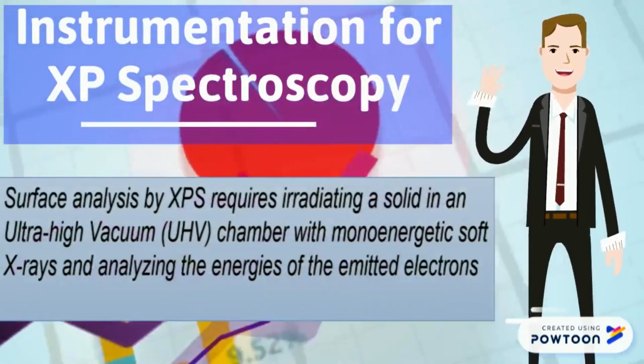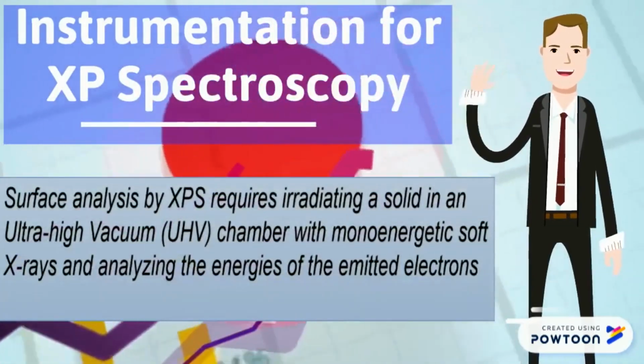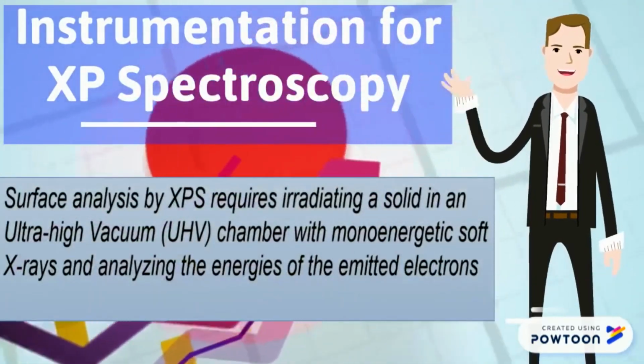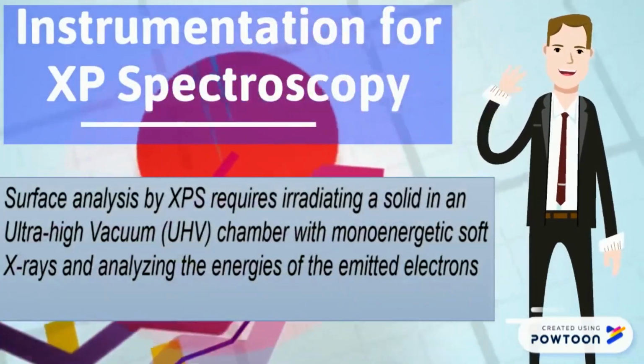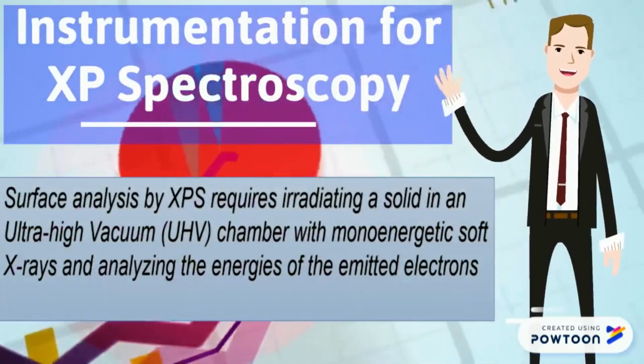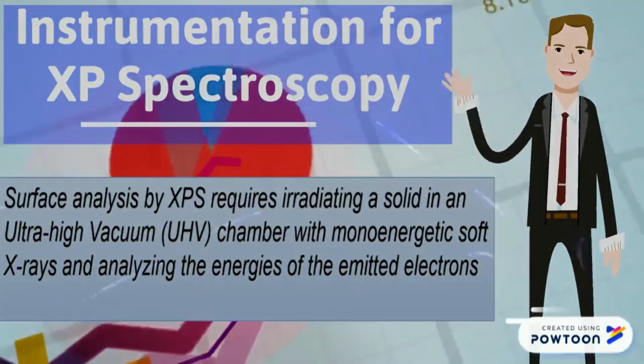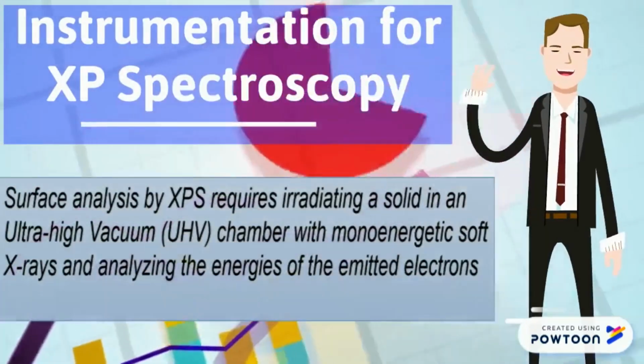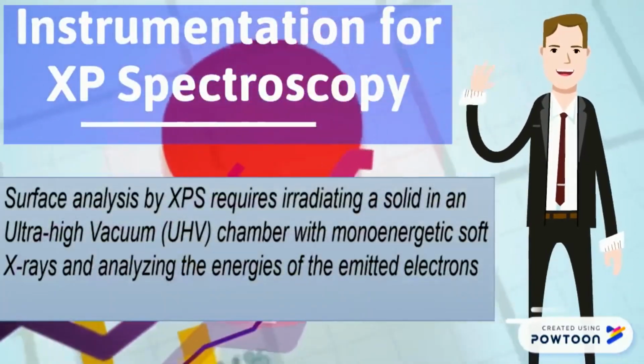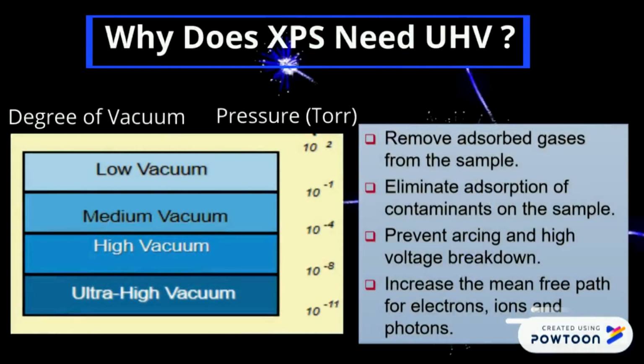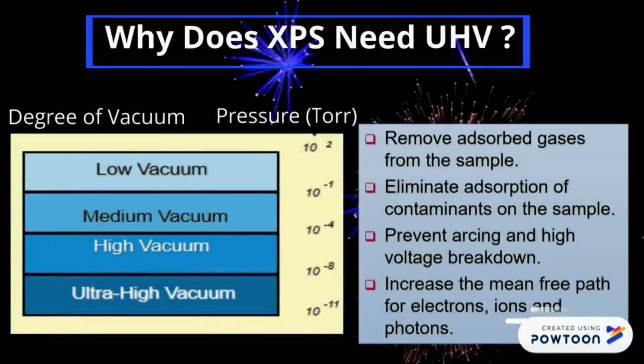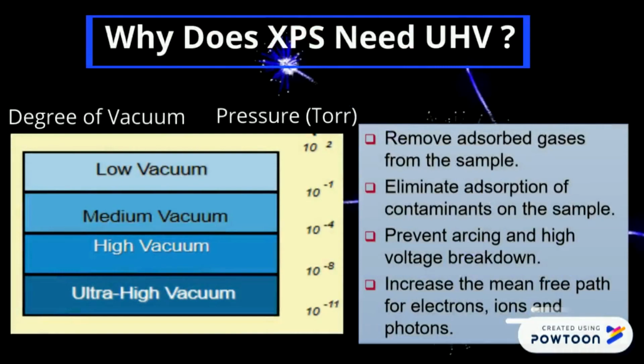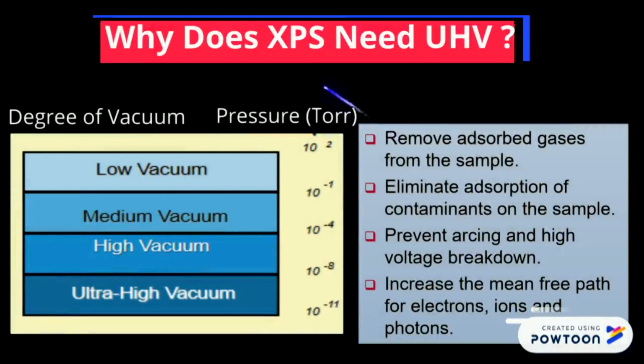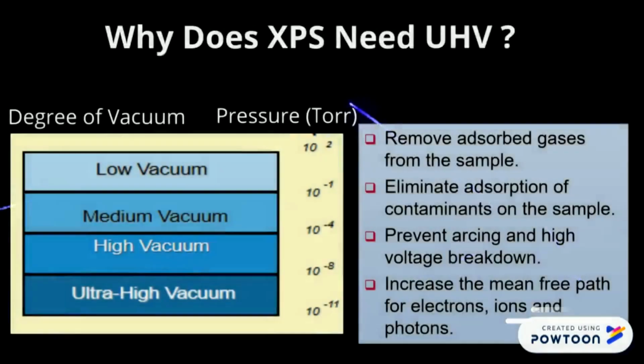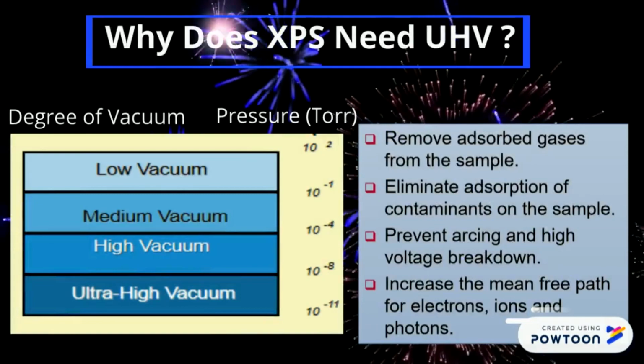Instrumentation for XP spectroscopy. Surface analysis by XP spectroscopy requires irradiating a solid in an ultra-high vacuum (UHV) chamber with mono-energetic soft X-rays and analyzing the energies of the emitted electrons. XP spectroscopy needs UHV to remove adsorbed gases from the sample, to eliminate adsorption of contaminants on the sample, to prevent arcing and high voltage breakdown, and to increase the mean free path for electrons, ions, and photons.